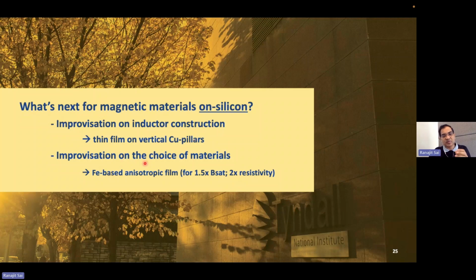And then we have done some improvisation of the choice of material. If we choose a better performing material than the state of the art, like the cobalt zirconium tantalum or cobalt zirconium tantalum boron based CZT or CZTB material, say Fe based magnetic material can have 1.5 times more BSAT, that means better current handling capability, and 2 times higher resistivity. It can be even higher, but 2 times we are demonstrating here today. 2 times higher resistivity means the eddy current loss will be significantly lower, maybe 4 times lower at higher frequency than CZT. So that will give the efficiency a real boost.